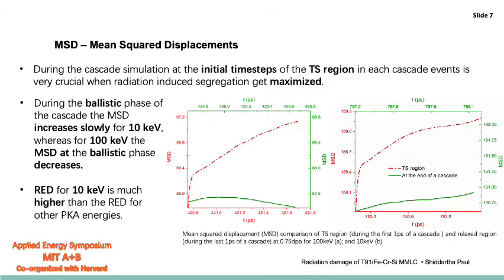In this figure, the mean square displacement has been presented for 10 keV and 100 keV energy. Observing those two figures, we can see the mean square displacement at the TS region, or the thermal spike region, is kind of the same. But at the ballistic phase of the cascade simulation, the mean square displacement increases slowly for the 10 keV primary knock-on atom energy, and for the 100 keV case, the mean square displacement is actually decreasing. So that's why you have seen an inverse relationship of the radiation enhanced diffusion with the primary knock-on atom energy in the earlier slide.